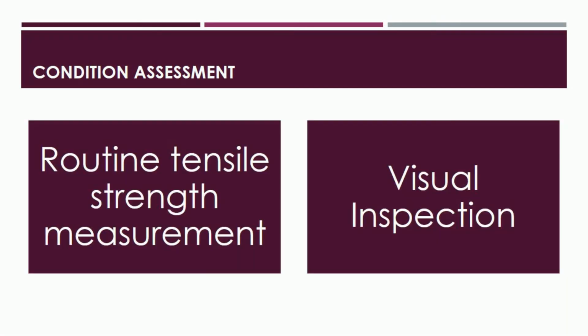Visual examinations can also give you a decent idea of how well an insulator is doing. Visual inspections can reveal the degree of surface pollution or flashover symptoms in porcelain insulators with broken or fractured sheds. Any degradation induced by corona can be identified using PD scans in the case of composite insulators. Hardware components that have corroded or are missing can also be recognized.